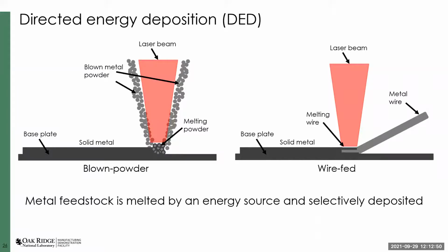So it's usually either an electric arc or laser beam, and some kind of feedstock that is fed directly into that source to melt it and then deposit it on a surface selectively, layer by layer, as is traditional with additive manufacturing. The specific system that I work with is a blown powder DED system. So it uses a laser beam to melt powder that is blown directly into the path of the laser, which is then deposited onto the substrate beneath the laser.